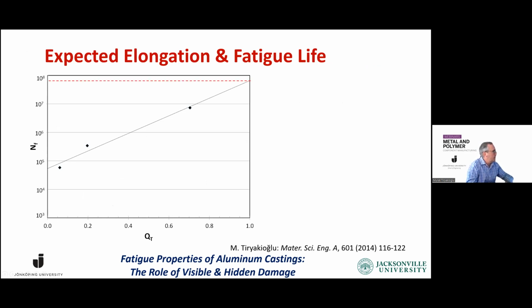And we can clearly see that if we extrapolate that to 1, which is basically free or very, very low damage, and if we are here at about 10% quality index or 90% loss to damage, then we can clearly see we can improve the fatigue life by 2 to 3 orders of magnitude. That was huge. But I had only 3 data points.